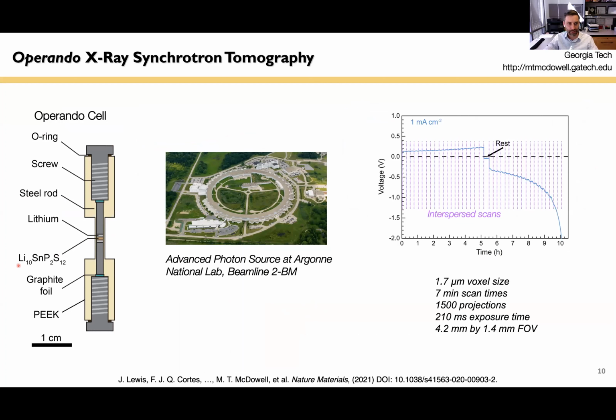The solid electrolyte we're using here is a different one than what I just showed you. This is what we call LSPS, lithium tin phosphorus sulfide. It has high conductivity, but as we'll see in a second, it's unstable. It's chemically unstable in contact with lithium. So we take this cell to the synchrotron, and because it's a thin cell, it's only about 1 millimeter wide here where the stack of materials is.